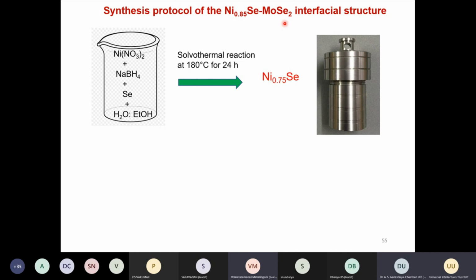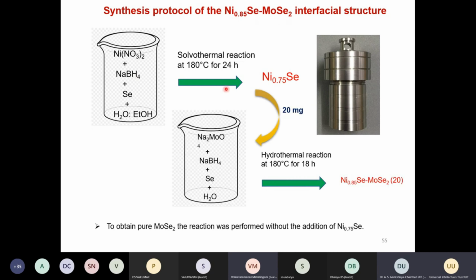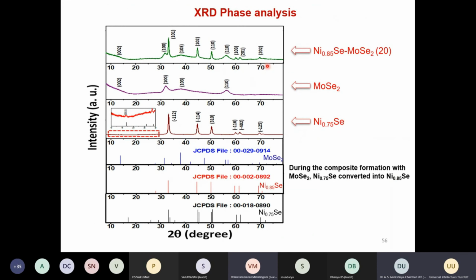Okay. So what we have done is a solvothermal reaction, where we have taken this nickel selenide 0.75 Se, which we characterized using XPS, and 20 milligrams of this is added to the molybdenum source precursor to get the nickel molybdenum selenide interfacial structure. What we observed is that this 0.75 Se, after reacting with the molybdenum in this hydrothermal reaction, basically converts into 0.85 Se. There is a slight phase change which happens during this synthetic process, which we have confirmed from the XPS as well as XRD measurements.